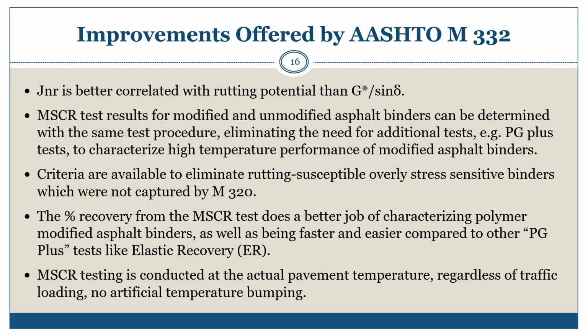Second, MSCR test results for modified and unmodified asphalt binders can be determined with the same test procedure, eliminating the need for additional tests such as PG Plus tests to characterize high temperature performance of modified asphalt binders. Also, JNR diff limits offer a criteria to eliminate rutting susceptible overly stress sensitive binders which are not captured by M320. The percent recovery from the MSCR test does a better job of characterizing polymer modified asphalt binders, as well as being faster and easier compared to other PG Plus tests like elastic recovery.